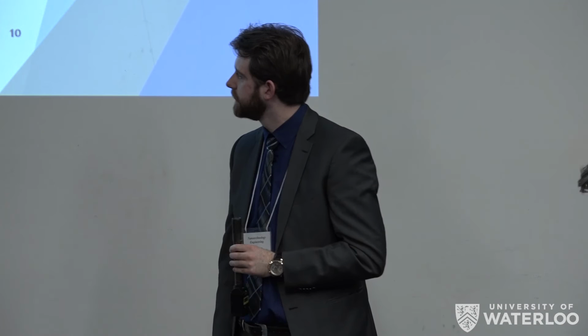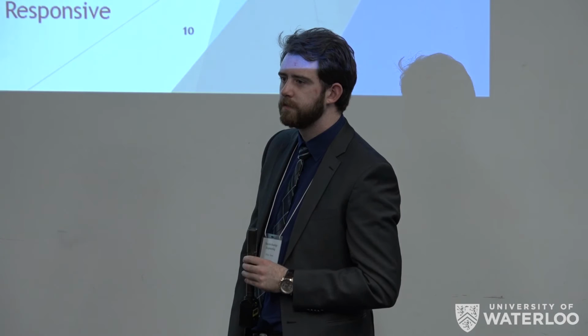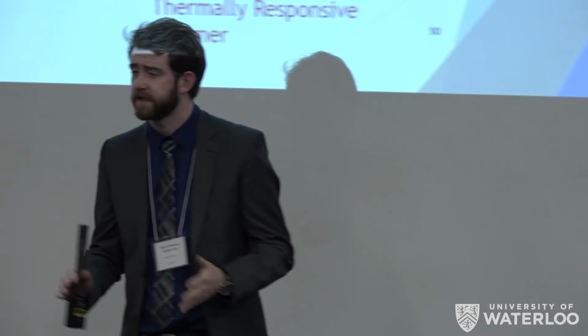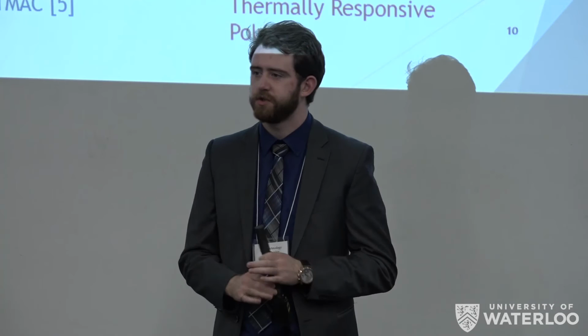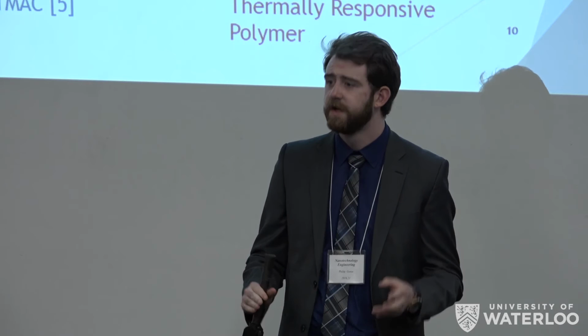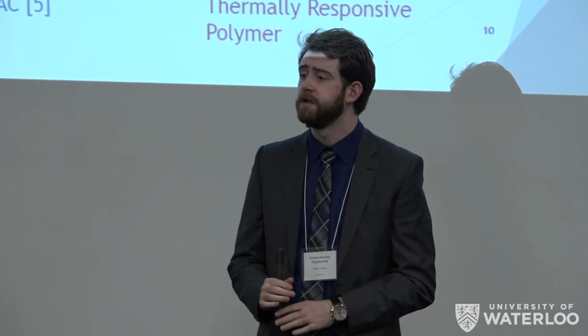Yes. You sort of alluded to the charge. Could you not just play with pH? Because, of course, that would change the number of amino groups, right? Yes. Because we need the positive charge to flocculate the algae, implementing a significant pH change would involve maintaining that pH through the growth tank. So we predict that it should be less expensive, at the very least, for us to provide a slight functionalization than to have to change the pH of a bulk solution.